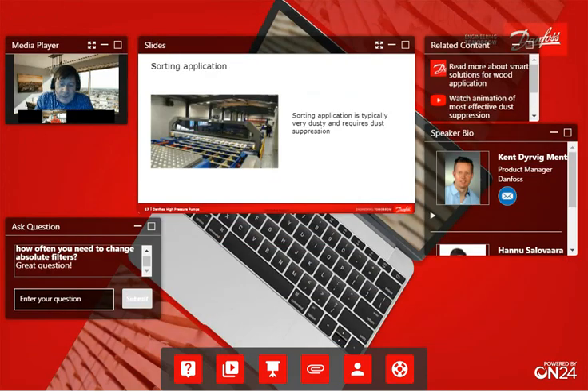So come back to this animation. The water droplets that we are producing have an average size between 20 and 30 microns, and this flying dust is typically from 5 to 20 microns. So they are very, very close to each other size-wise, and that's why the effect is much better than if we have, for example, big droplets which are just raining down. And also the density is much higher because we are producing so many more droplets from the same amount of water. That's why we are using less water for the same processes as earlier.